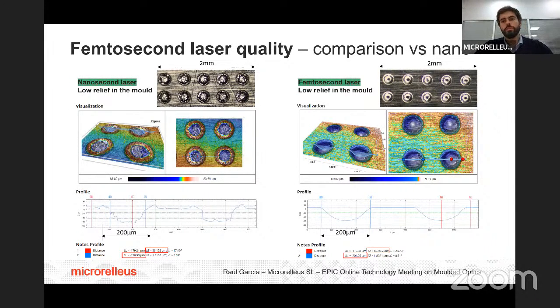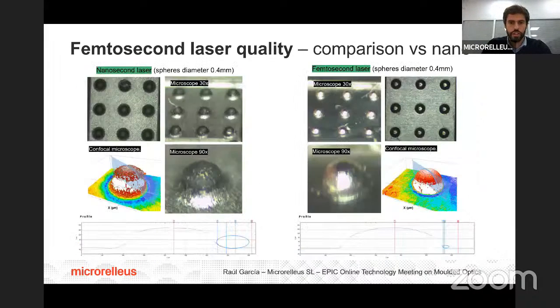Even if we can see two microstructures that seem to be the same, when we analyze with a confocal microscope, we see big deformation of the shape and the profile when using nanosecond, and very good definition when using femtosecond. The same here, where we can see the difference in very sharp edges and very good definition of the sphere in the femto.